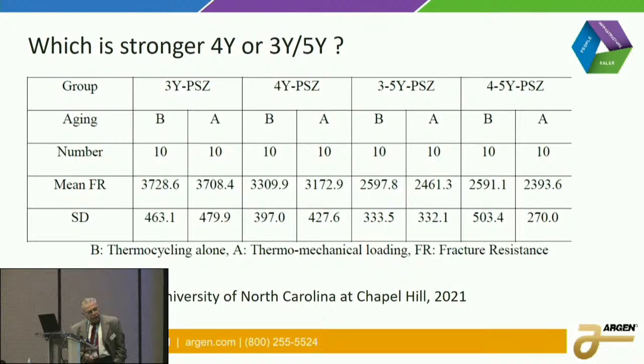There's one company that has a multi-layer route where they put the 5Y zirconia on top of 4Y in order to try and gain the strength from the 4Y, but they don't. They actually lose it because of the 5Y. And all of this is due to exactly what I was talking about a minute ago, and that is in some cases you're going to see tension on the occlusal plane, and when you get that circumstance, the strength of the material is going to go down. So staying with a 4Y zirconia throughout the entire thing, you have 1,200 megapascals throughout the entire unit, and you don't have to worry about losing strength or losing translucency for that matter.